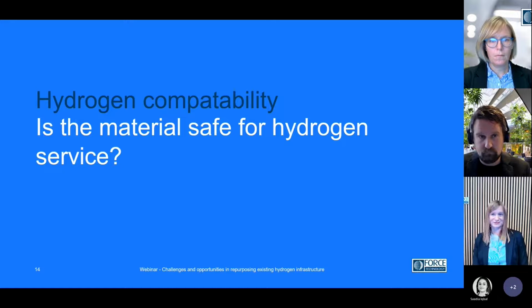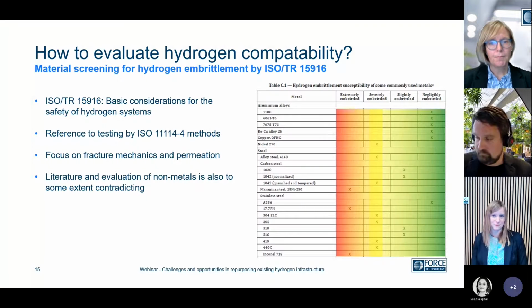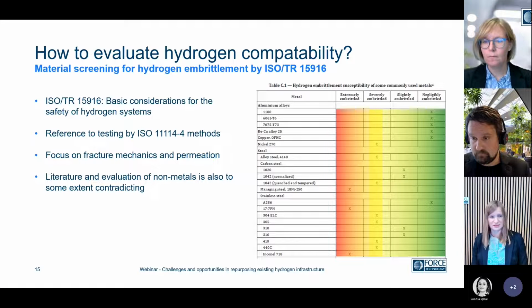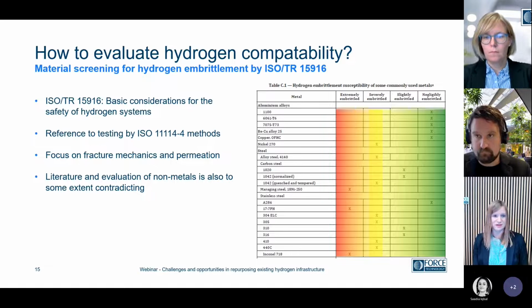But oxygen or not, how do we in general evaluate material compatibility in hydrogen infrastructure? It's not only just the pipeline steels, but also the associated components. And one generally accepted approach is to consider the ISO TR 15916, which is basic considerations for the safety of hydrogen systems. And it contains several tables. Well, one of them lists several materials ranged from extremely embrittled to not really embrittled at all, based on a focus on fracture mechanics and permeation testing. And we see especially the austenitic materials performing well, and even low alloy steels being quite embrittled.